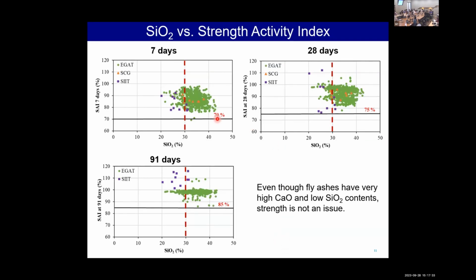This one shows the relationship between silicon dioxide and the strength activity index at 7 days, 28 days, and 91 days. These are the results from 3 laboratories: EGAT, SCG, and SIIT. We can see that even though fly ash has very high calcium oxide or low silicon dioxide content, the strength is not an issue.